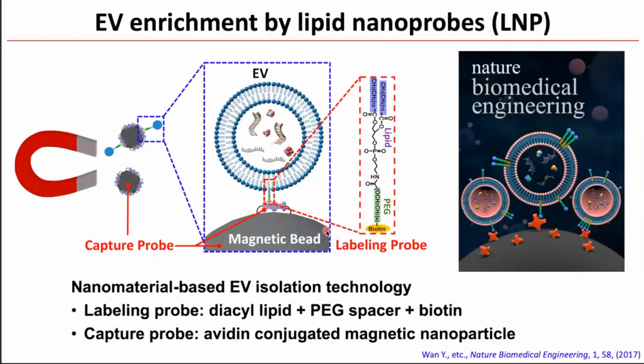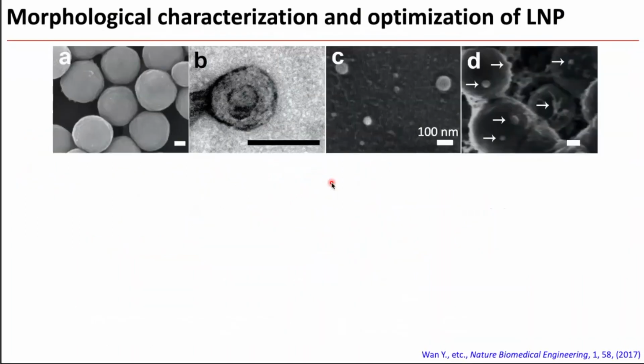So the way this nanomaterial system works is we first mix the labeling probe with the sample. What happens is this probe will spontaneously insert into the membrane of the extracellular vesicles. So basically, we tag those vesicles in this step. And then we use the magnetic bead to pull those vesicles down. So here are some electron microscopy images of the capture probe, the vesicles before they are captured and after they are captured.